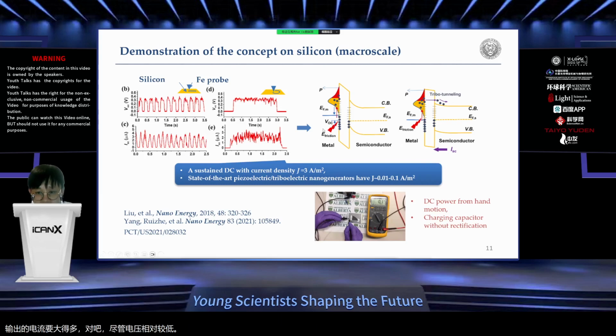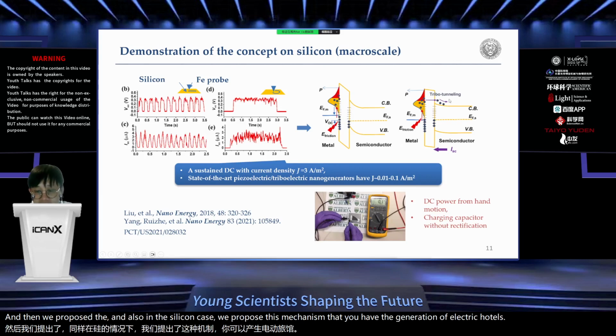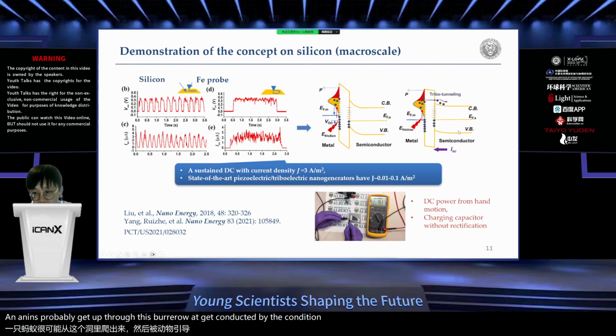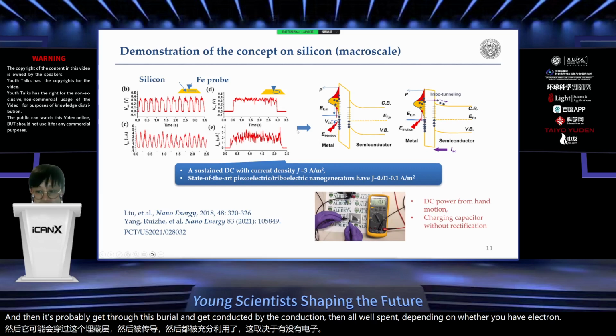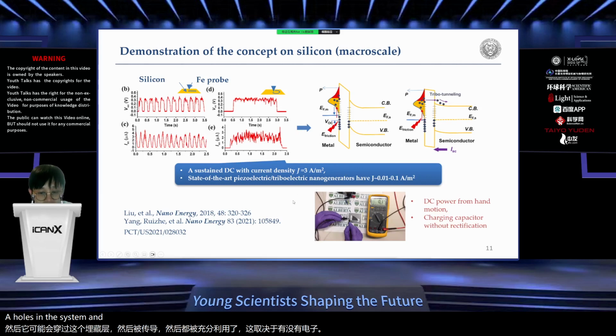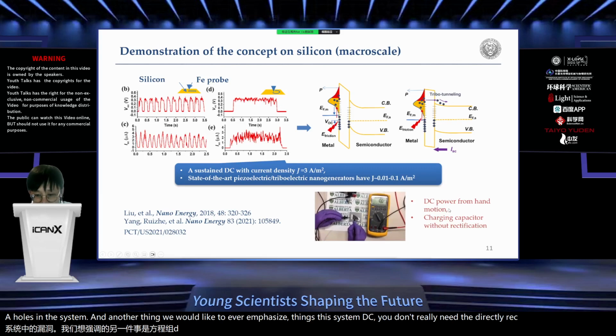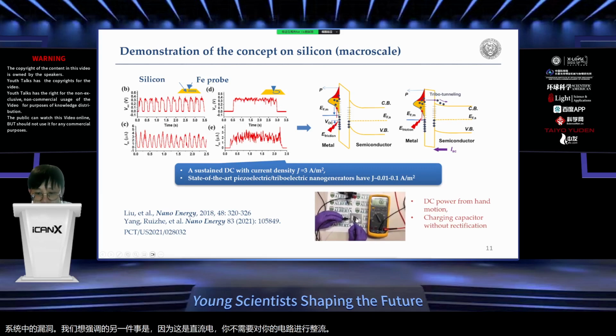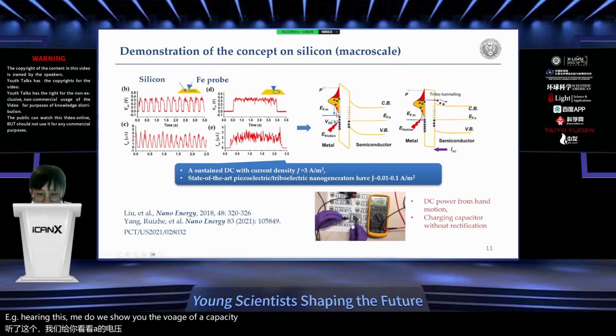And then in the silicon case, we propose this mechanism that you have the generation of electron-hole pairs, and then they probably get through this barrier and get conducted by the conduction band or valence band, depending on whether you have electrons or holes in the system. And another thing we would like to emphasize, since this is DC, you don't really need rectification in your circuits. For example, here in this video, we show you the voltage of a charging capacitor by simply rubbing a stainless steel probe on a piece of silicon.